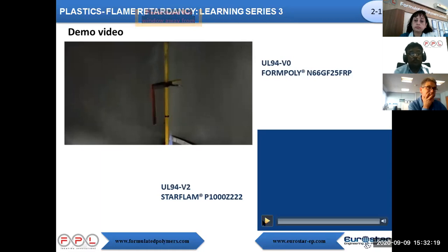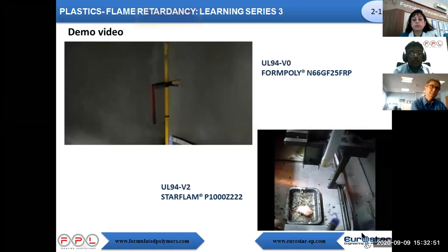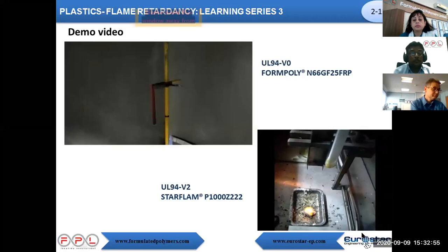Then we move on to the UL94 V2 test performed with Starflam P1000Z222. Procedure conditions are the same as we saw in the earlier video. The specimen is ignited for 10 seconds and withdrawn. Then again we ignite the same specimen for another 10 seconds. Then we need to record the dripping and cotton ignition condition. Then by referring to lab observations and the acceptance criteria shown in the table, we can easily rate the tested material's flammability.